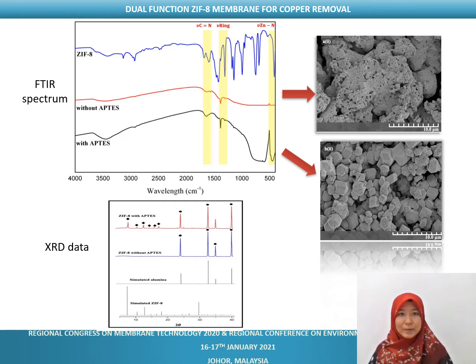In 2013. The FTIR spectrum also compared the functional group existed in the ZIF-8 membrane prepared in the presence of APTES and without the presence of APTES. The intense band observed for ZIF-8 alumina hollow fiber membrane with APTES modification revealed the formation of ZIF-8 layer on the alumina support. The C=N stretching band was identified at 1589, whereas the peak at around 1380 attributed to the entire ring stretching fingerprint.